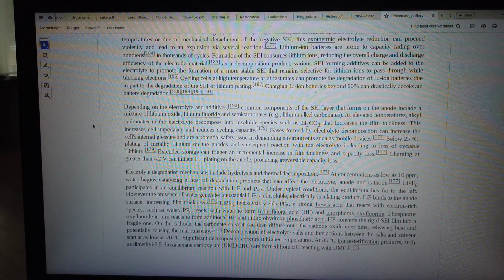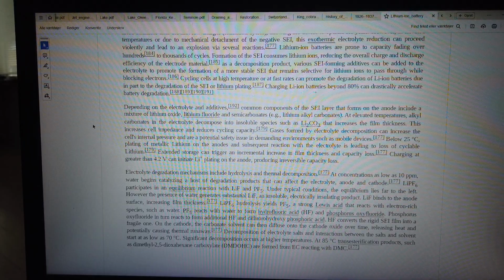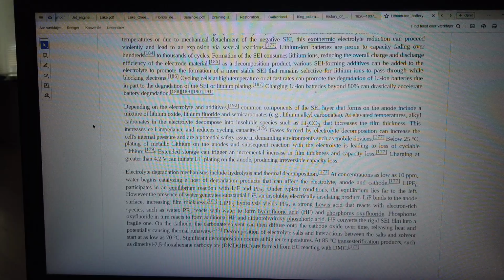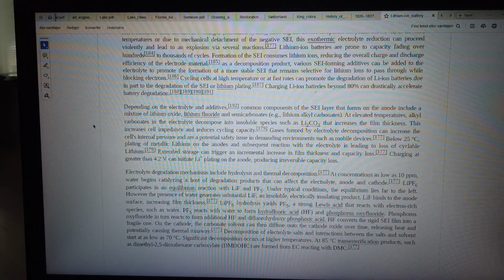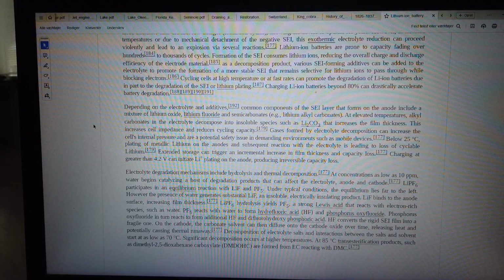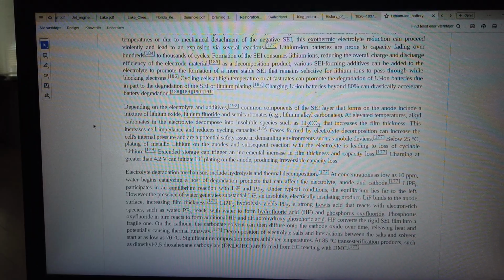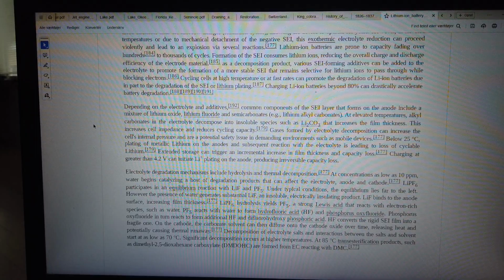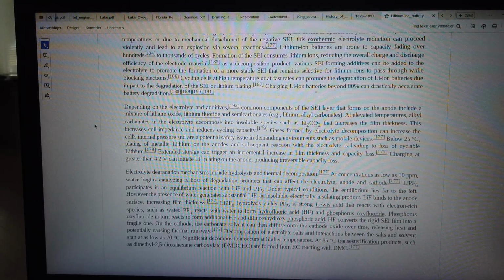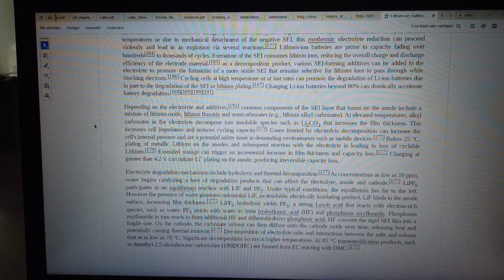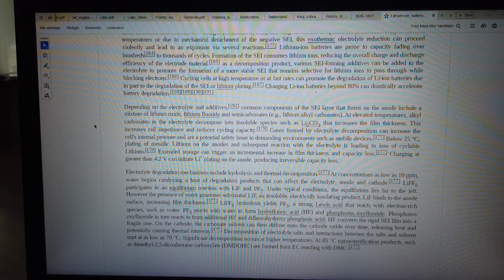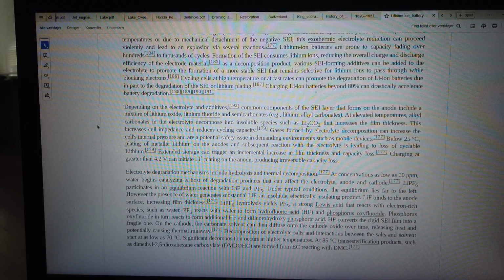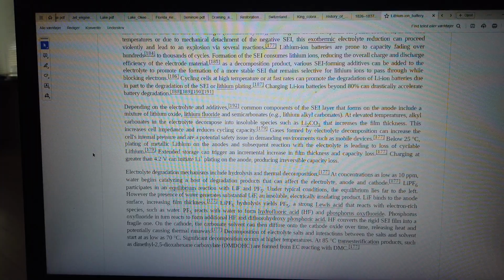Gases formed by electrolyte decomposition can increase the cell's internal pressure and are a potential safety issue in demanding environments such as mobile devices. Below 25 degrees C, plating of metallic lithium on the anodes and subsequent reaction with the electrolyte is leading to loss of cyclable lithium. Extended storage can trigger an incremental increase in film thickness and capacity loss. Charging at greater than 4.2 V can initiate Li plating on the anode, producing irreversible capacity loss.